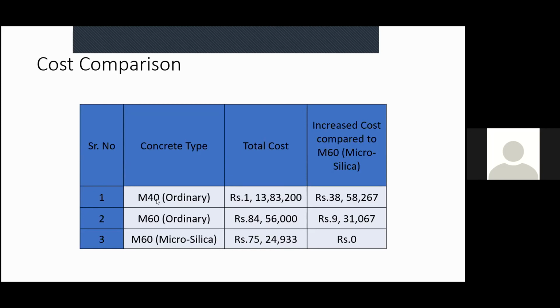And if we are comparing with M40, then we could save 38,58,000 rupees. So using microsilica for just 6.4%, this can save, because general concrete grade is M40, and against that we are getting M60 microsilica grade, and we can save almost 30 to 35% of cost in skeleton.